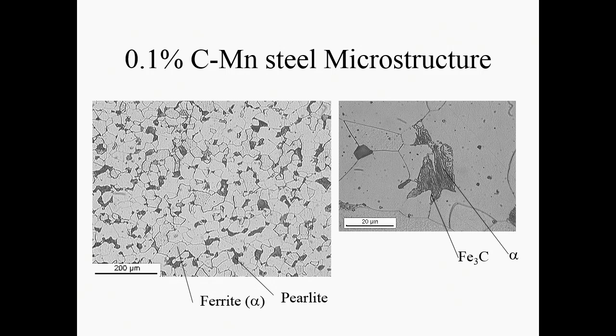You can see the grains here are quite big. These are 20 micron plus grains. Controlled rolling will take that grain size much, much smaller. When the pearlite forms, it's not formed effectively as a single crystal, was there? No, this is what we call a colony. So if you went into here and you went with a very high powered electron microscope, you'd find that there were lots of different bits of iron carbide, slightly different orientations, and you can get bits growing like this and like this and like this together. So if you go at a high enough magnification, it's single crystal, but that's true for everything.